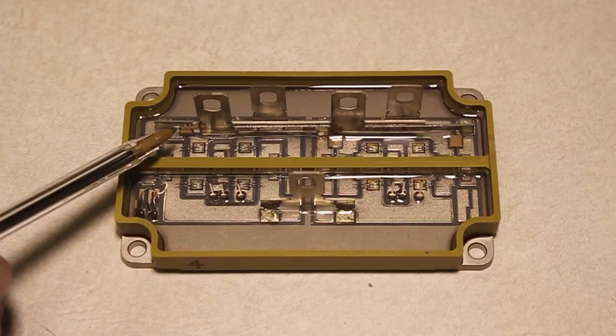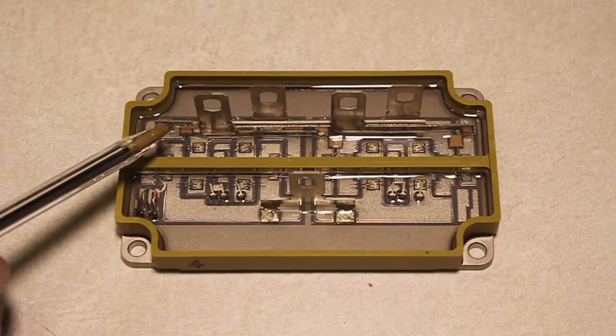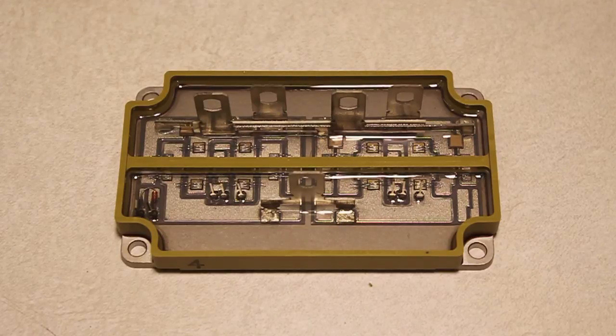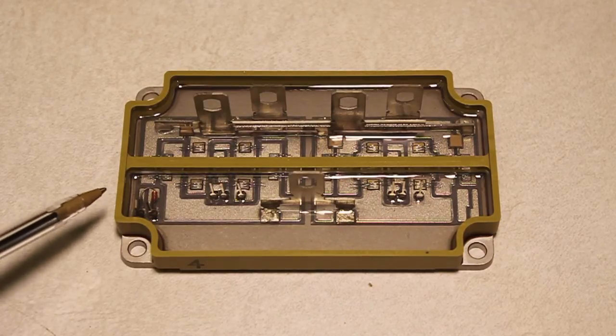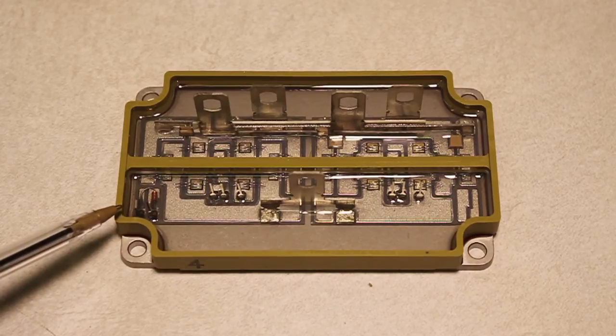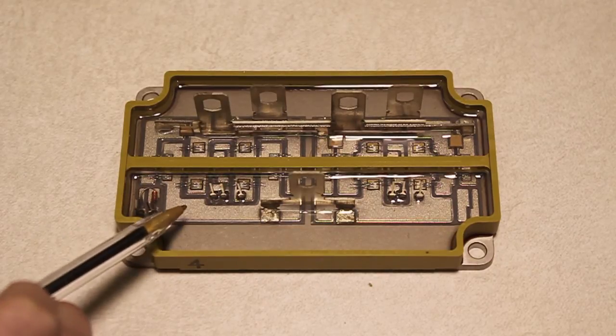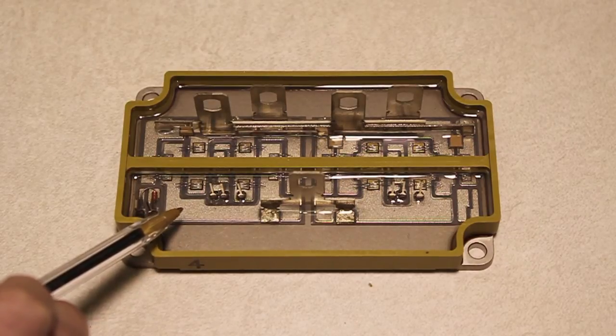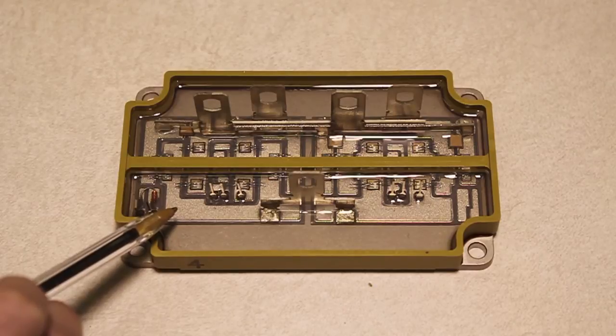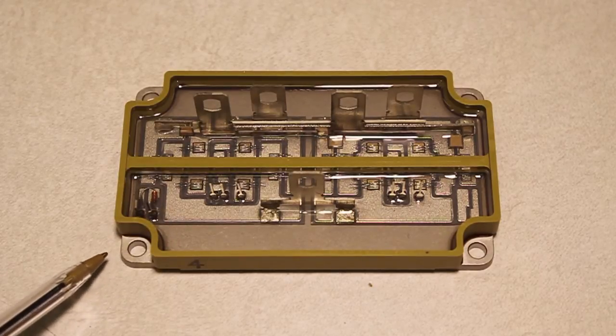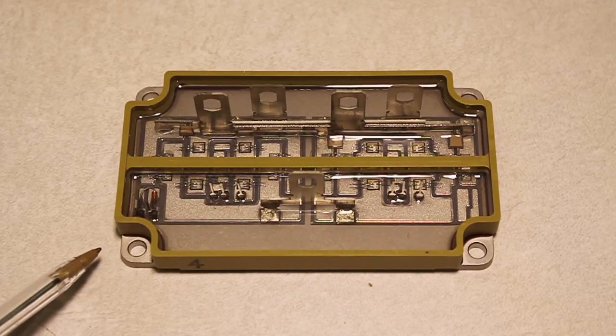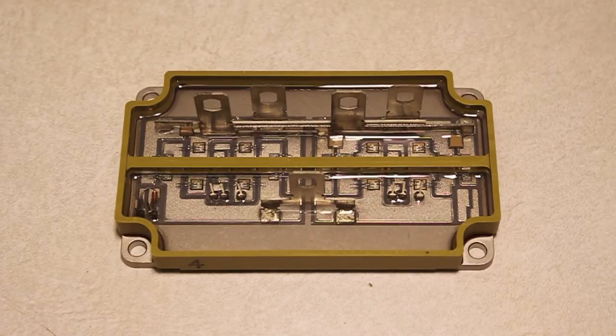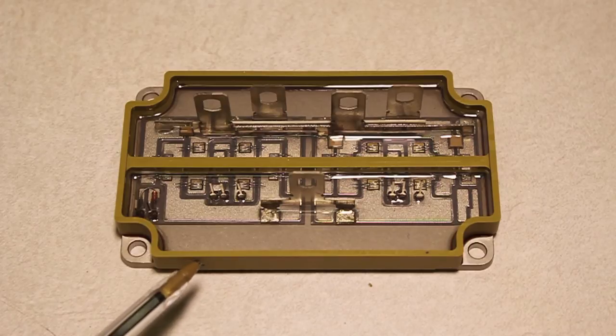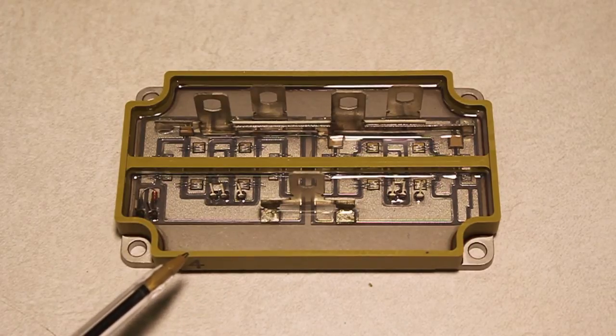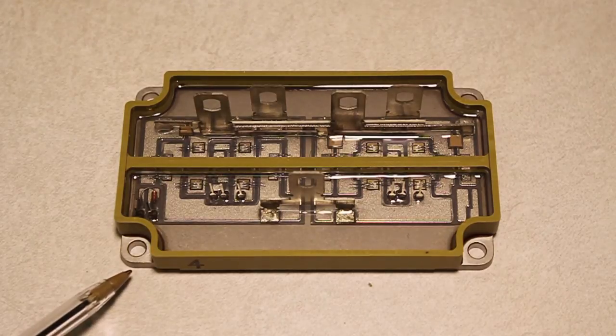High-temperature ceramic capacitors are embedded inside the module for decoupling from the bus bar parasitics. The module also includes an embedded NTC thermistor for sensing of the substrate temperature. Aluminum nitride was selected as the substrate material due to its high thermal conductivity and close CTE match to silicon carbide. SiC was chosen as the base plate material due to its low CTE, light weight, and reasonable cost. The substrate is bonded to the base plate using epoxy adhesive. The housing is made of Torlon, a high-temperature plastic, and is secured to the base plate with silver epoxy.